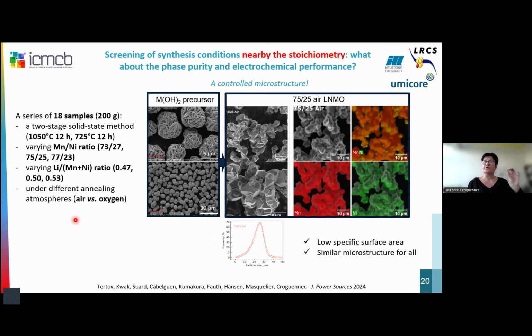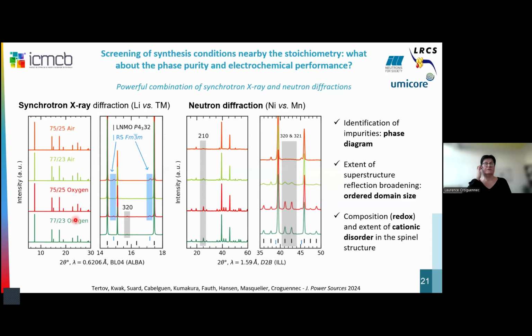So I will not give you all the details of the results obtained. I will just focus on a few results in order to highlight the main results. So first of all, I would say the originality of this work is also that we combine synchrotron X-ray and neutron diffractions in order to really take advantage of both techniques. And here I took four samples in order to highlight this. So 75-25 here under air or oxygen in red are the stoichiometric materials, and 77-23 in air or under oxygen are the manganese excess materials.